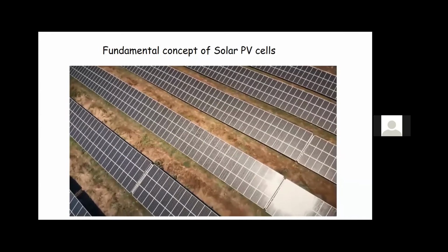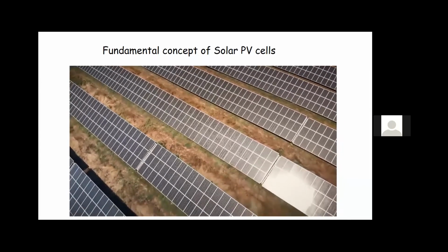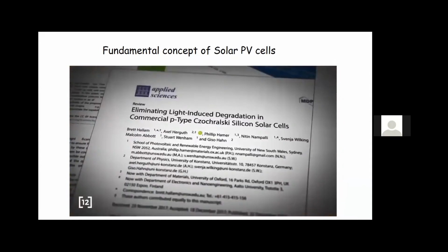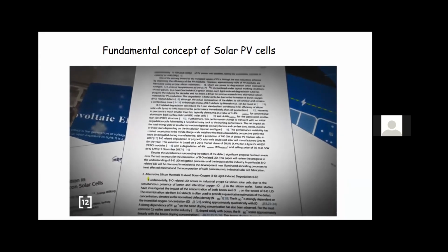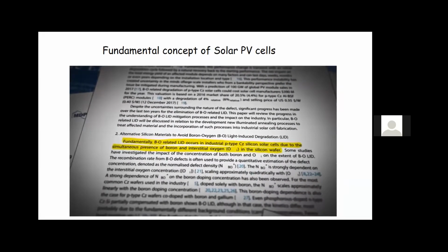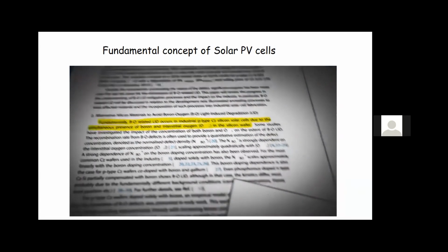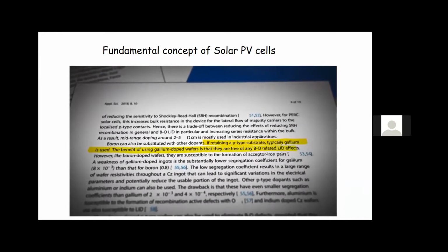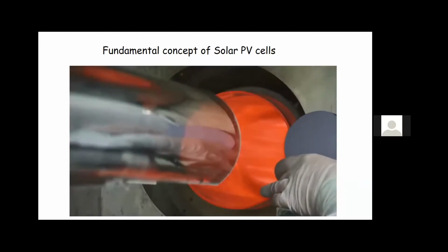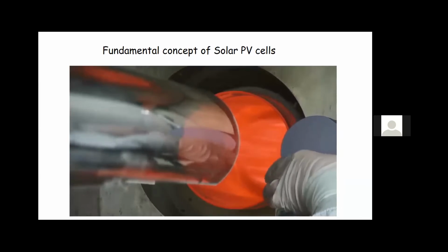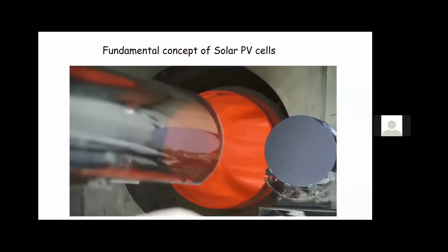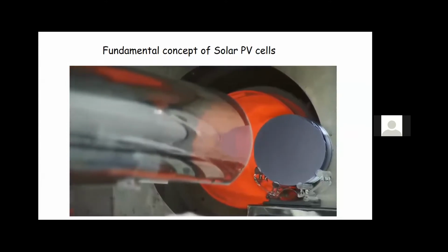So, what was happening to cause that drop to 18% after a couple of hours of operation? This problem was the focus of hundreds of scientific papers, and many found clues to the problem. Many noted that the efficiency drop was correlated to the concentration of boron and oxygen in the silicon, and noted that the drop did not occur when boron was substituted with gallium. Thus, it was known a boron-oxygen defect was causing the issue. Others found that the defects could be reversed by heating the silicon in the dark at 200 degrees for 30 minutes, but it would return once again upon exposure to the light.